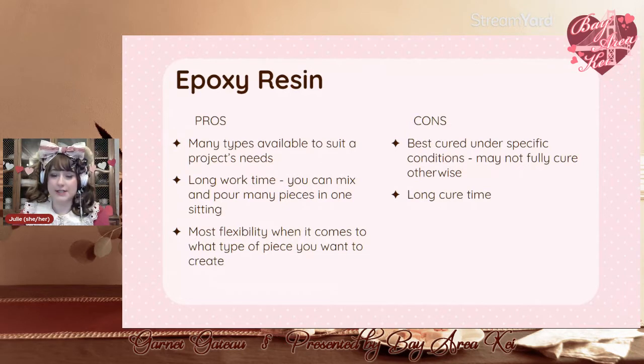The downside of epoxy is that it can be very finicky if you're not using it under the right conditions, meaning that it likes a certain ambient room temperature and you need to be working in a dry environment because epoxy resin does not like moisture. If you get any water in the mixture, then it bubbles up and turns into foam and it looks really weird and spooky.